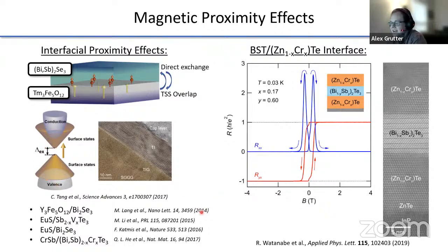And this has been tried since 2013, 2014, with everything from yttrium iron garnet to europium sulfide to chromium antimonide. And in fact, the Tokura group in 2019 successfully realized the quantum anomalous Hall effect in bismuth antimony telluride interfaced with zinc chromium telluride. And this is a doped ferromagnet here.